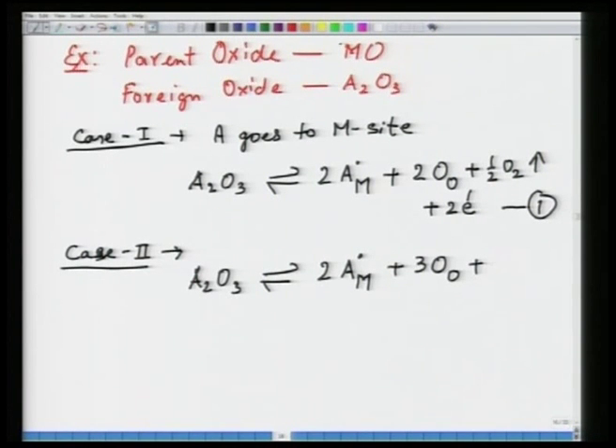Parent lattice has one M site for one O site. Now, here you have created 3 O sites. So, for three of these O sites, you need to have 3 M sites, and you are filling only 2 of them, which means one of the O sites, which is created as a result of 3 oxygens going to oxygen sites, you will have 1 metal site which would be vacant. So, you will have V_M with 2 negative charges. So, now this is balanced site and mass wise as well as charge wise. So, this is another possibility that could happen when you put A2O3 impurity in MO solid.